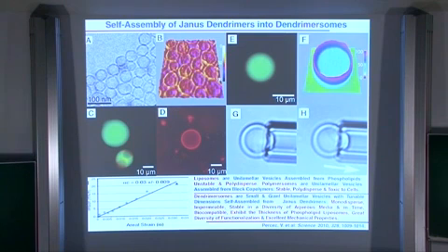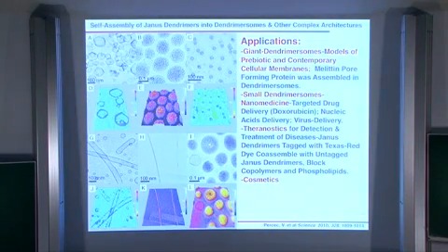Our molecules are monodispersed and impermeable. Impermeability is as good as the best molecules. They are stable in a diversity of aqueous media and in time, biocompatible, exhibit the thickness of phospholipid liposomes, and have great diversity of functionalization and excellent mechanical properties. Not only do they form vesicles, but they form the larger diversity of additional complex structures exhibited by any natural or synthetic class of molecules, including phospholipids and block polymers.